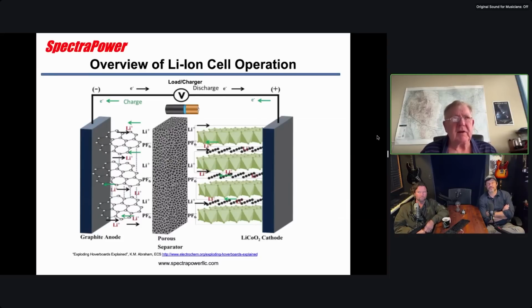transformation, if you will, where the lithium has to migrate through what's called a solid electrolyte interface. The SEI layer is how it's referred to, and that SEI layer is really critical for safety. I don't show it here. I think I have it on some other slides, but I'll just explain it, because that's how the ions move from the electrolyte solution into the solid graphite.